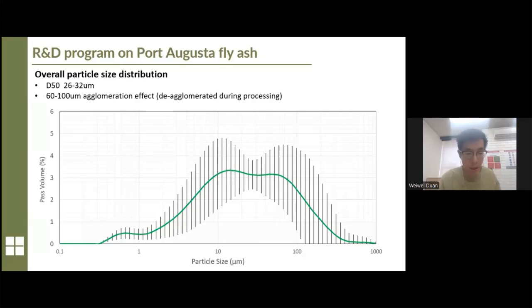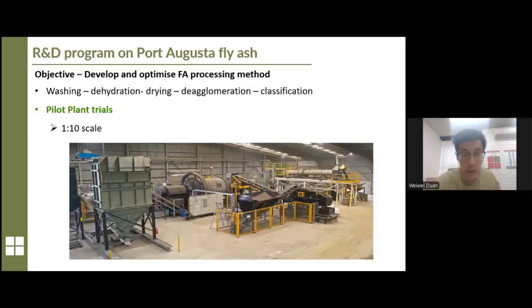That is the overall particle size distribution of all the 130 samples we have taken. The D50, the average size, is between 26 and 32 micrometers, which is really fine. There is an agglomeration effect at around 60 to 100 micrometers, which needs further processing to get it de-agglomerated. So that's the first stage.